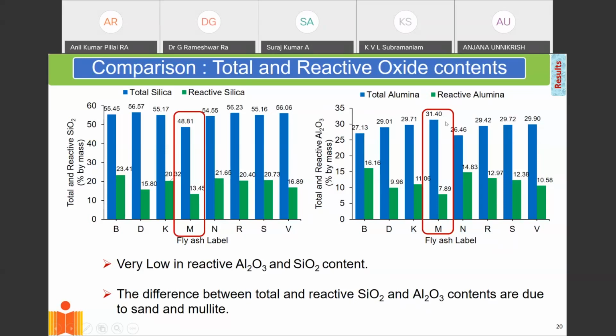Fly ash also contains alumina, and alumina is also a reactive material. Although in traditional cement chemistry, which is basically calcium silicate chemistry, we do not consider alumina, it is present there. And if I look at total alumina in the fly ash, it is typically anywhere from 27 to 30%. But the reactive form of alumina is always a much smaller amount. Now, in traditional cement chemistry, we do not talk about alumina, but when we start looking at alternate cements, the alumina starts playing a critical role, and I'll talk about that in the next few slides.